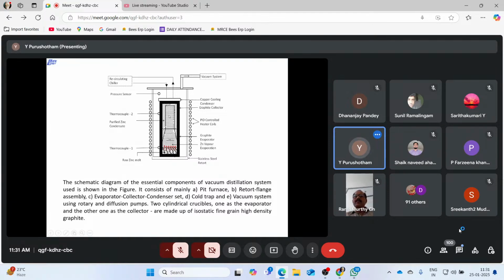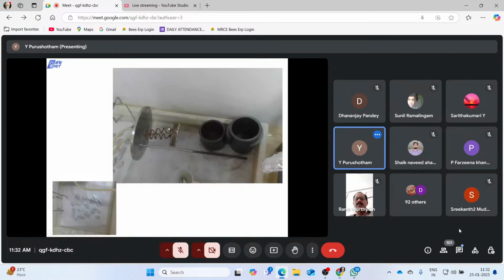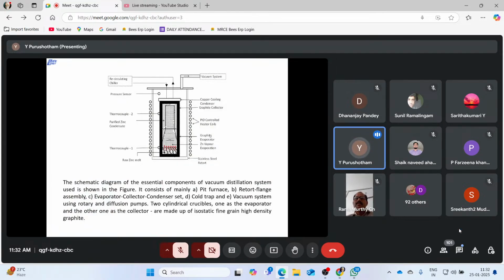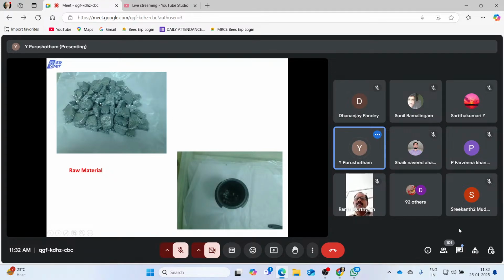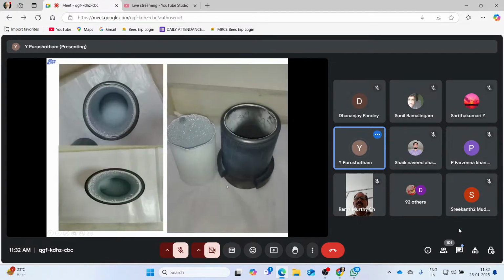Copper cold water is sitting on this one. So this will be at a lower temperature compared to the bottom crucible, and all these vapors will go and condense in the top crucible. That's why we are keeping an empty crucible there. You can see here the raw material we are loading in the bottom crucible, and after distillation, in the empty crucible, all these impurities have condensed, and you can get the same shape here.